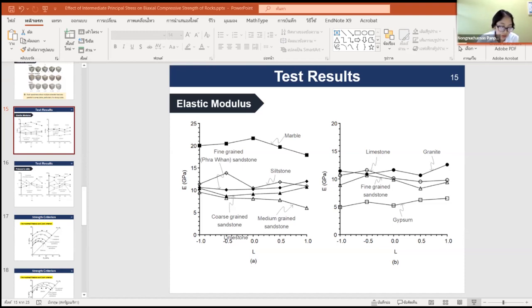And discussions and conclusions. The findings from this study can be summarized as follows. First, elastic modulus and Poisson ratio tend to be independent of the load parameter. Second, intermediate principal stress affects rock strength. Modified Weibull and Cook criteria can well describe rock strength under biaxial conditions. And last one, factor of safety analyzed from biaxial strength are higher than those based on uniaxial compression.